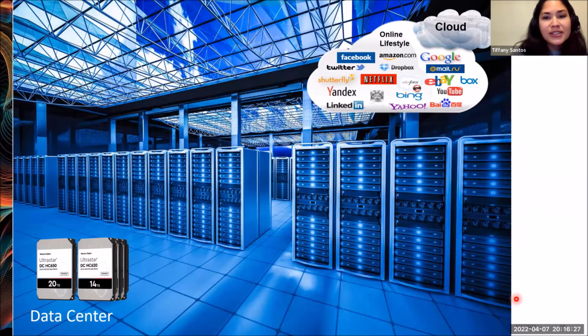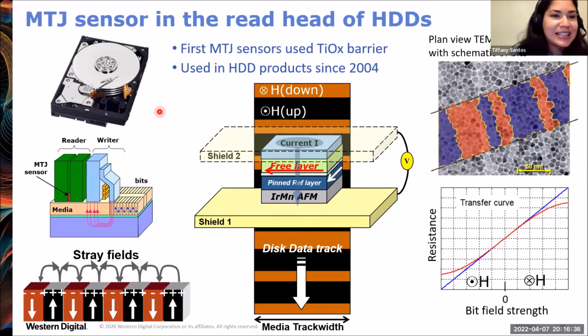Okay. And here's how that process works. So I'll tell you a little bit about how the magnetic tunnel junction functions inside the hard disk drive. So here we have the inside of the hard disk drive, where this is the spinning disk here where the bits of data are stored on a magnetic film that coats the surface. If you take a powerful microscope and look at this film on the disk, you'll find that it's made up of lots of magnetic nanoparticles. Groups of them come together to form a bit, and that's shown schematically here in the red and purple colors for bits, zeros and ones, lined up here in a track in the film.